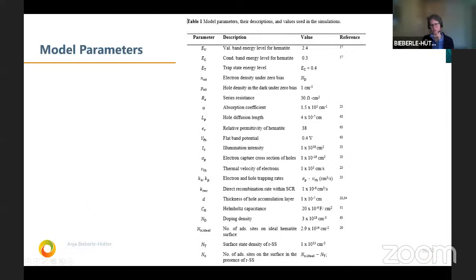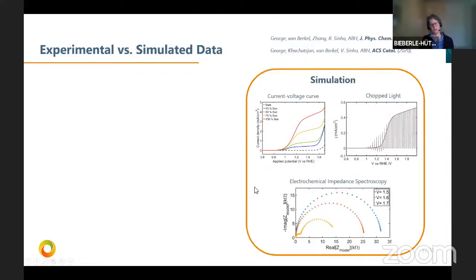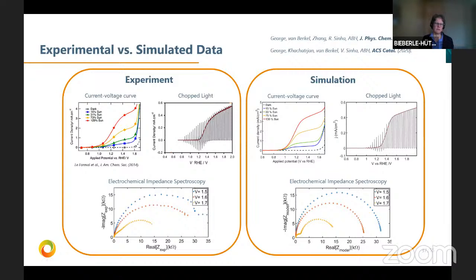We also use a lot of model parameters in our simulations, and we try to get them from the literature. But as I say, a lot of values are not very well known. And what we can do now, we can really calculate current densities, but we can also calculate chopped light measurements, and we can calculate impedance spectra. So these are really simulations from this electrochemical model. And these compare actually rather well to experiments.